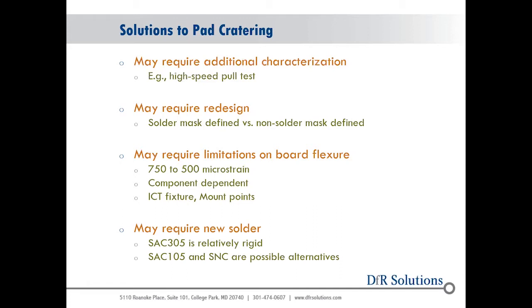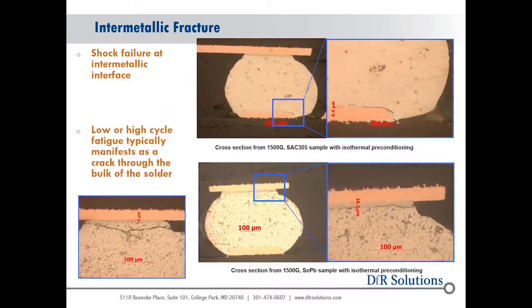During ICT, you may have to add mount points. You may consider going to a different solder, but my opinion is that if I have a shock problem with SAC 305, yes, switching to a SAC 105 or an SNC or SN100 or a SAC M may get me a little bit of margin, but I still have a problem, and I'm still going to have failures. There's just not enough to eliminate the issue. It may be a combination of solder changes with additional mounting to mitigate it.